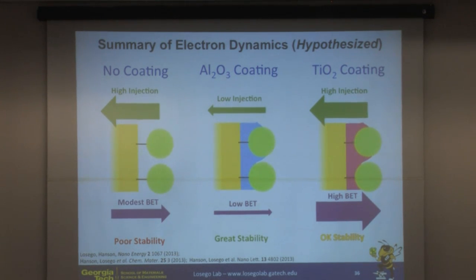Unfortunately, when we add the alumina coating, even at 3 angstroms or so, we really hurt the injection in the device. But it also prevents back electron transfer. So it's really acting as an insulator, as one might expect. And we can't inject, nor do we have electrons coming back. With the TiO2 coating, what we found is we maintain about the same high injection rate as far as we could detect. But we see even higher back electron transfer rates than we had seen previously. So TiO2 just seems to be acting as a conductor, because often the scaffold itself is TiO2. So we're just making the scaffold closer to the molecule itself.